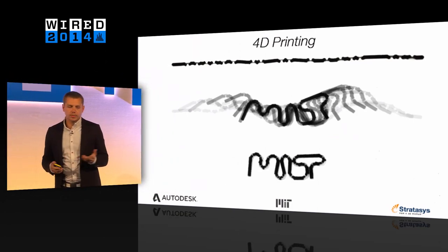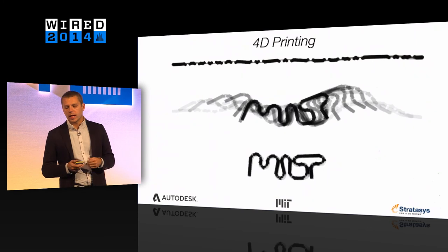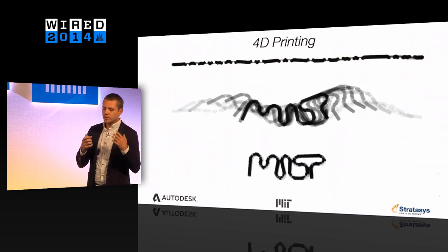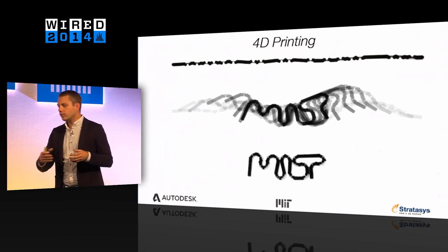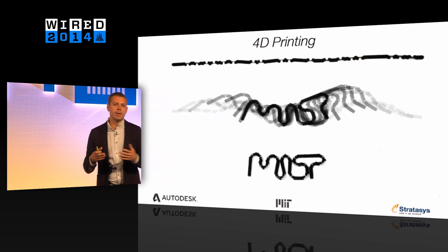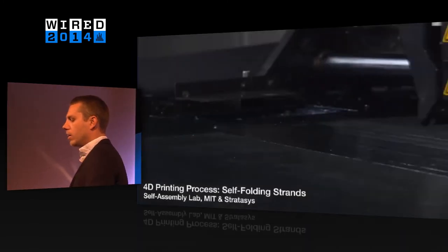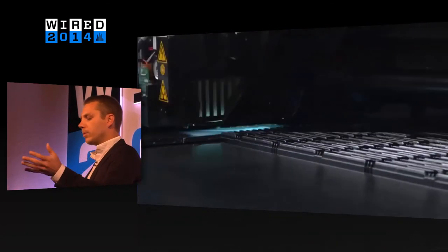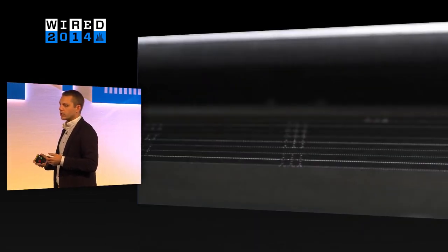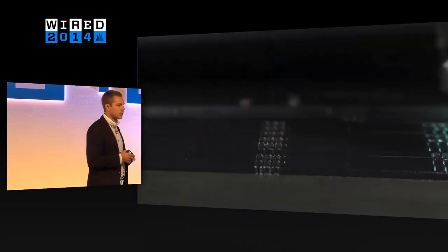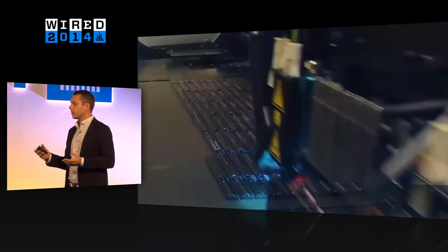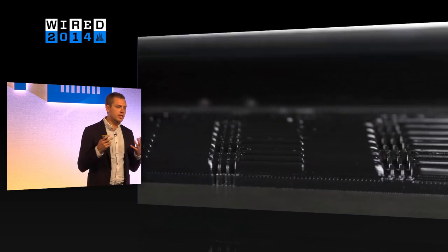We've done a number of different projects. Probably our most notable work is something called 4D printing. We took the idea of 3D printing and said we want to add time as the fourth dimension — we want things to not just be static objects but to transform, reconfigure, and have a life that adapts over time. We collaborated with Autodesk and Stratasys on this project, depositing two different materials: a rigid plastic that provides geometric information and structure, and an expanding polymer that expands 150 percent when it meets moisture, allowing it to go from one state to another.